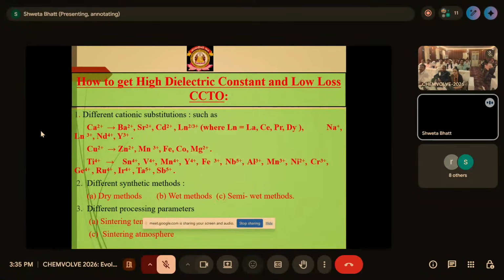Also, we have to use this method to synthesize this material, because the synthesis and processing parameters also affect the dielectric constant of the material as well as the dielectric loss. As we know, when we synthesize the material, there are different types of processing, such as sintering temperature and calcination temperature. Along with that, we also have to use different types of atmosphere. So we can change the properties of these materials by doping.